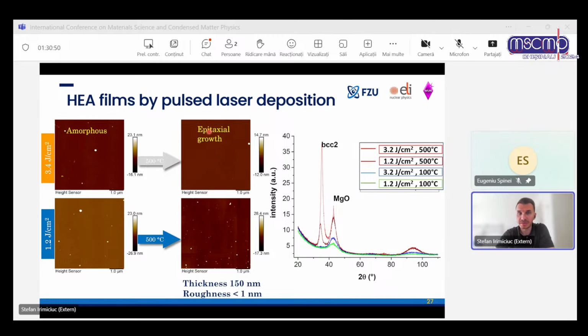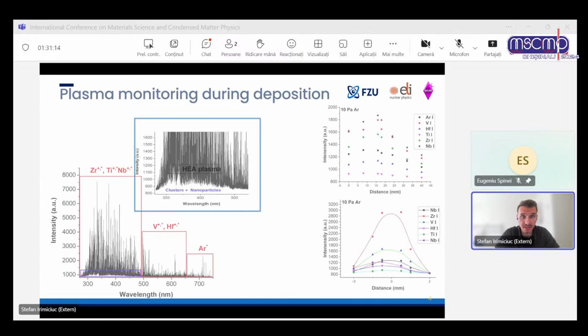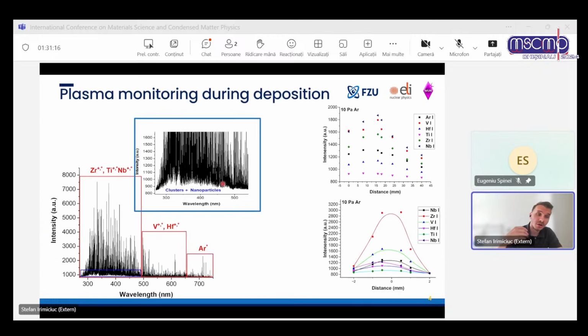This is an optimistic assessment of the films, but what we found with PLD, and maybe this is because the plasma is too complicated, because you have the high energy, and because it's not an equilibrium deposition technique, you can capture and freeze the high entropy phase better. And this is something that we applied later, and we also did the optical emission spectroscopy during the deposition of the films, and what we saw actually confirmed the tests that we did.